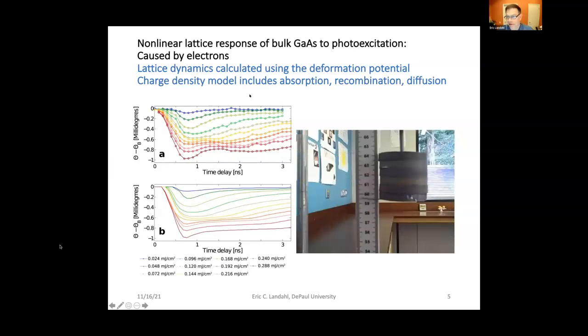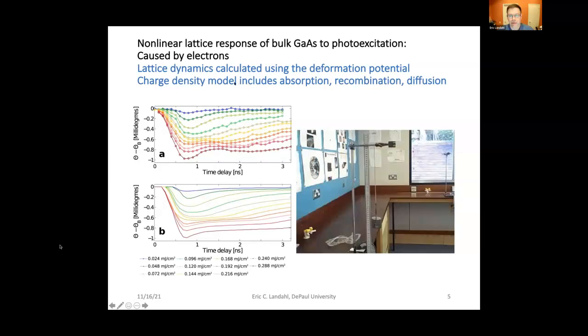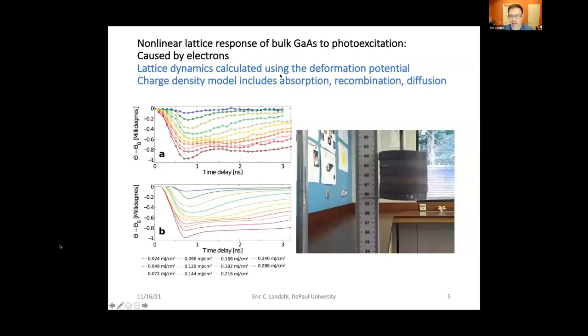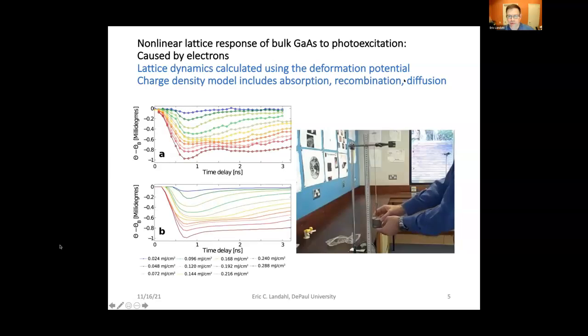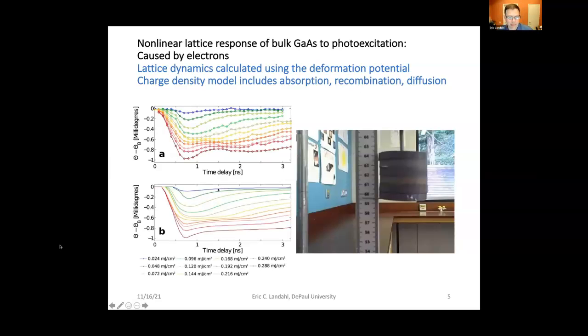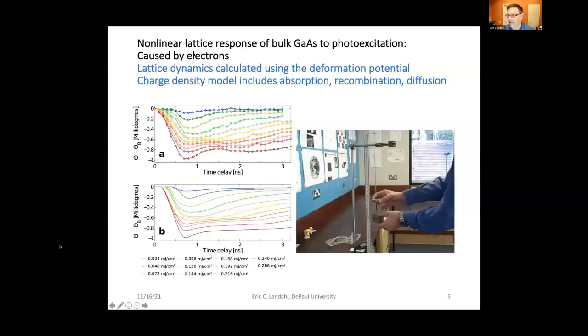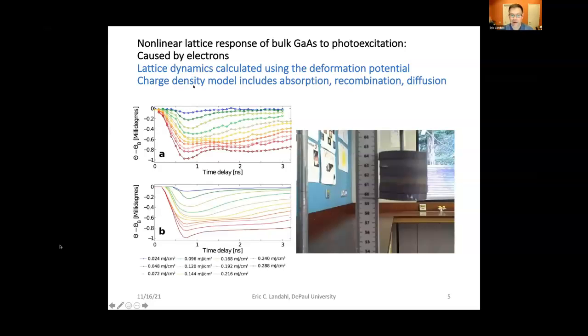Modeling this is done with a dynamic diffraction model that also includes charge density everywhere in the sample, including absorption effects, recombination effects, and diffusion. So we're quite confident that we can recapitulate it, but the point for today is that this is also caused by electrons. That is the electrons moving, which we directly view in these measurements.